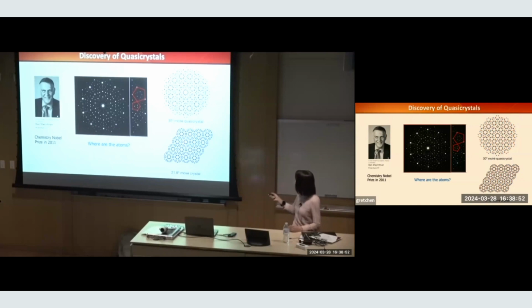What's interesting is both of these angles are energetically stable. Chemists can find them in their chamber. They grow them, and they either grow in a line way, or they form quasicrystals or these minimal period Moiré crystals. Our colleagues found them using STM, because the flakes were very small when CVD grown.